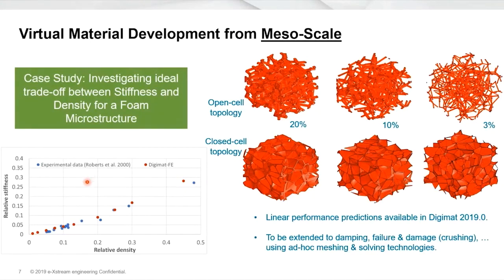The idea of this case study is to find the best trade-off between the relative density and the relative stiffness for such microstructures. And as we can see, the Digimat tools can predict accurately the experimental data plotted here in blue dots, by comparison to the red dots corresponding to the Digimat FE predictions. This is a first step and can be extended to more complex behaviors like the prediction of damping, failure, and damage using ad hoc meshing and solving technologies.